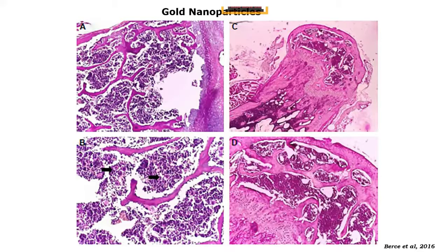For example, if you have something like a 2 nanometer gold or a 5 nanometer gold, it is considered to be among the most toxic conditions, and results in rapid cell death by necrosis, well established. Whereas if you go above 20 nanometers or even above 15 nanometers, you do not see these toxic effects with the gold nanosystems.